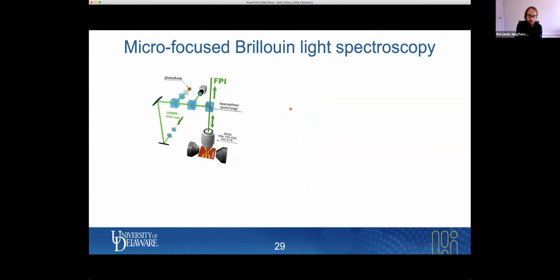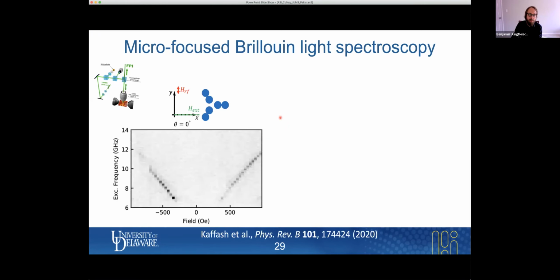So let's first perform the same type of experiment as before. We do basically an FMR measurement with BLS, and we focus the laser on one spot, change the field and the excitation frequency, and we see those modes. In this case, the resolution is not very good. But nonetheless, we see here an agreement between BLS and the FMR measurements. The advantage here is we can do the space resolved measurements.